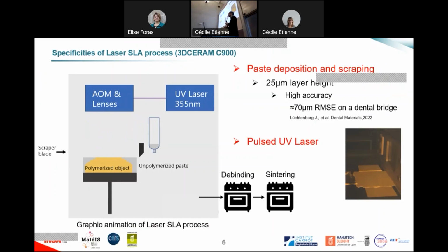So what is specific for this technique compared to other photopolymerization techniques is that we use paste deposition. We don't use a cube with resin on it. And we have very thin layer height, which permits us to have a very good accuracy. So you have this error of around 70 micrometers on a dental bridge, which are surfaces that are pretty difficult to make. And also we have a good surface state.